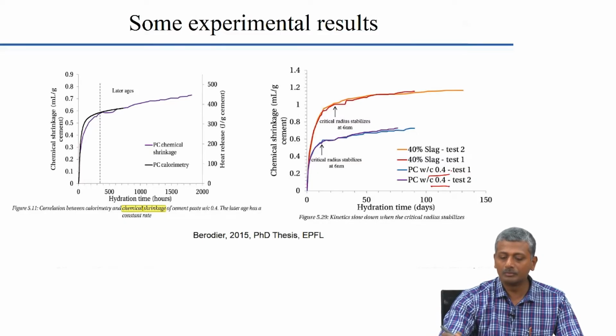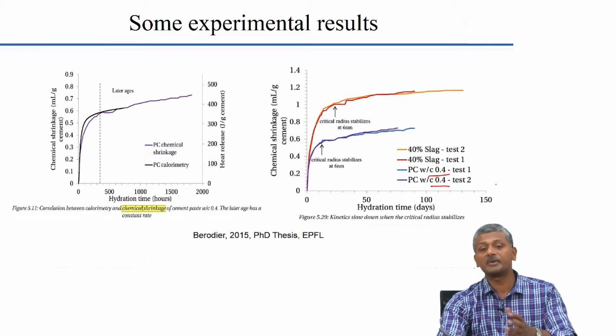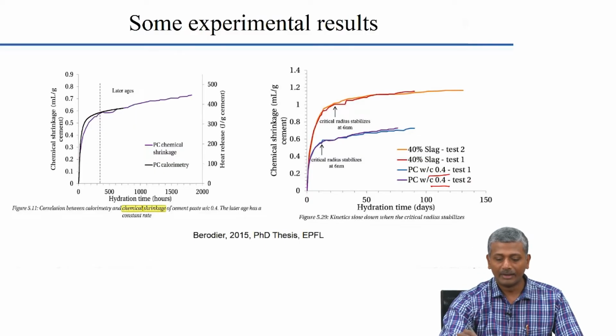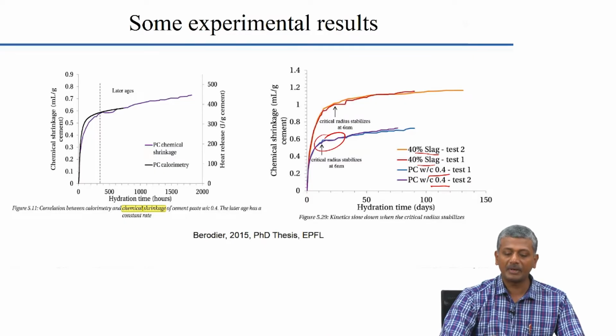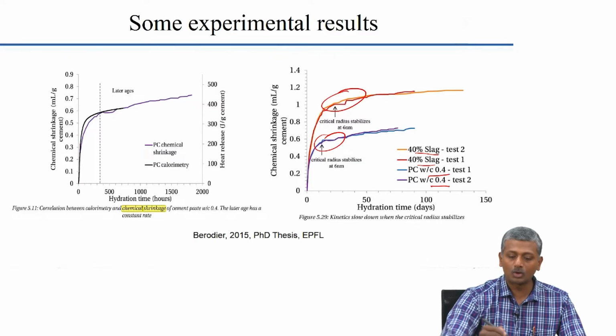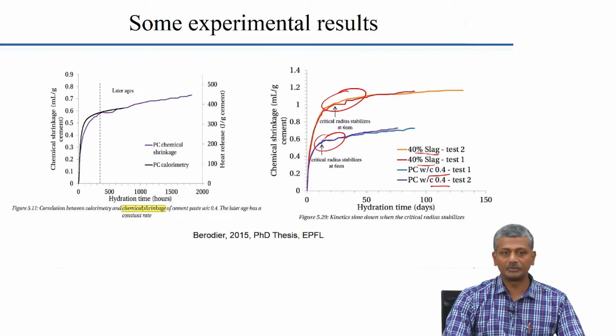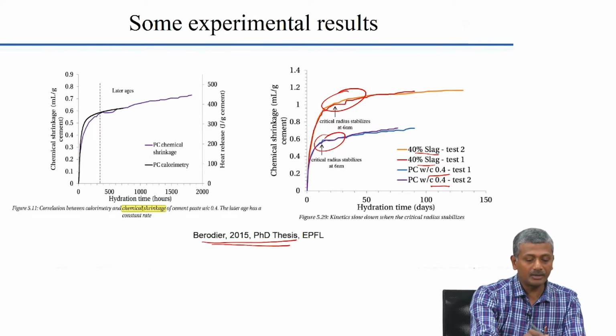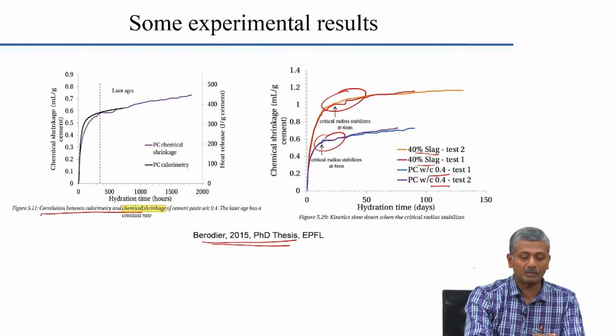So, here there are some experimental results that are given for two types of concrete. You have Portland cement paste with a water cement ratio of 0.4 and the same paste when it is replaced by 40% slag. So, you can see here that for the plain cement paste, the extent of chemical shrinkage is going to be lower than what you observe with the slag.